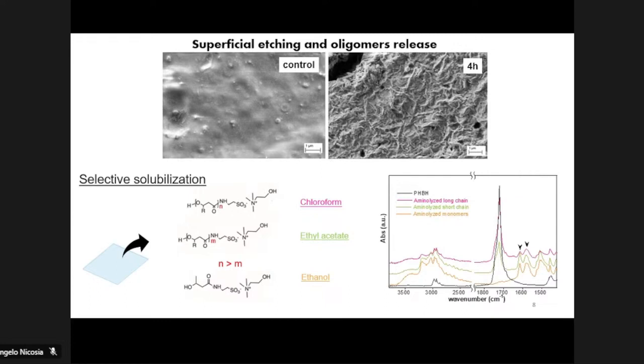In fact, in the reported FTIR spectra, it's possible to note that for the second fraction, the intensities of carbonyl absorption of ester bonds and of amide peaks are quite the same. Finally, the third fraction was collected in ethanol and is composed of aminolyzed monomers. In fact, it's not possible to detect any absorption of ester bonds.